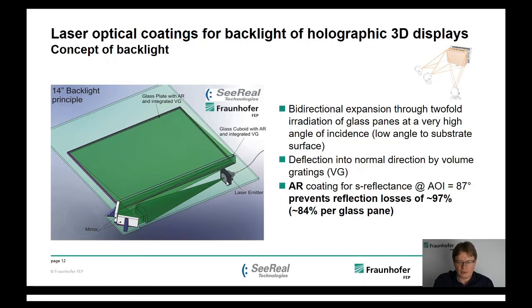With the first lens, it's upscaled to the centimeter range, a few centimeters, and this beam is irradiated at a very high angle of incidence onto a first glass plate. Here it enters this glass plate and comes out perpendicular on the other side through a volume grating. Already here, the beam is upscaled to the size of this first glass plate. Then it enters the second glass plate, which has the size of the display. Again, at a very high angle of incidence, it comes out perpendicular, and in the end it's scaled up to the size of the display. It's quite a nice way to expand this laser beam, but it has a problem.